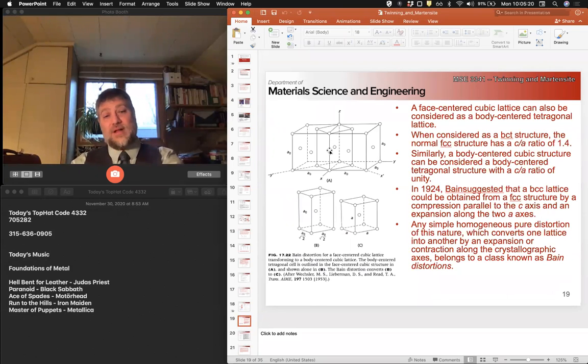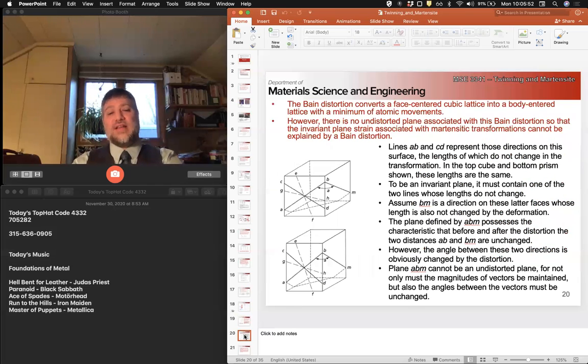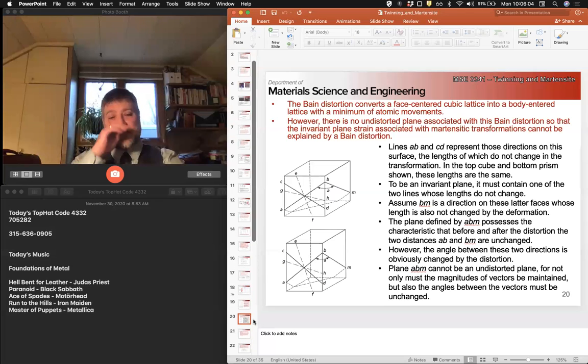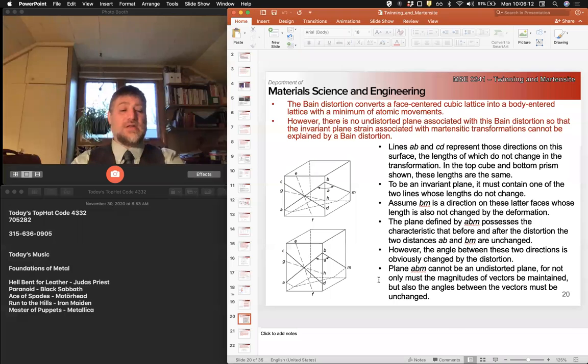Because there is no invariant plane, right? So in order to get an invariant plane, we need something beyond this Bain distortion. We don't have the two shear planes where we have perfect atomic congruence between the FCC and the BCT. So in order to get that relationship, we need something more, right? And that's a series of steps that are called the phenomenological theory of Martensite. And we'll talk about those on Wednesday. Okay? So Wednesday we'll talk more about Martensite.